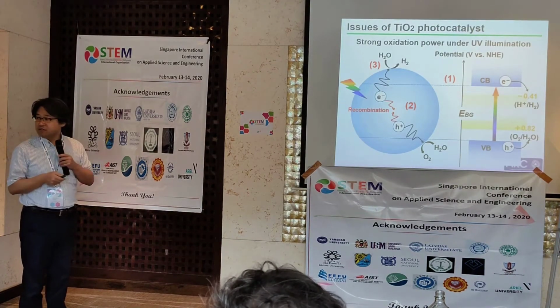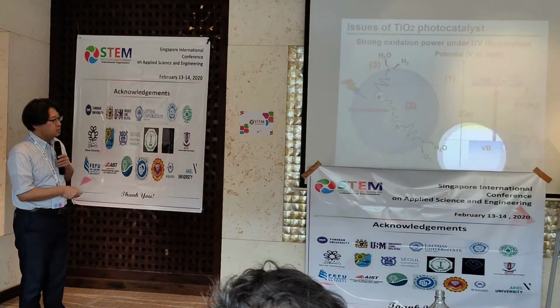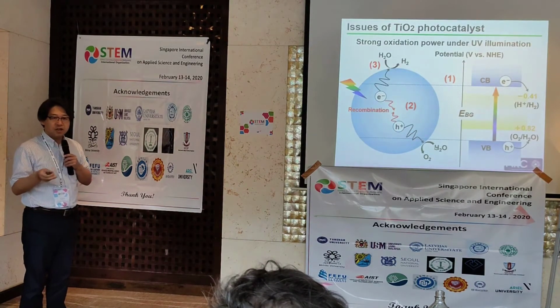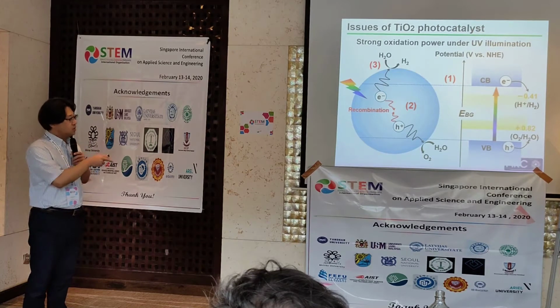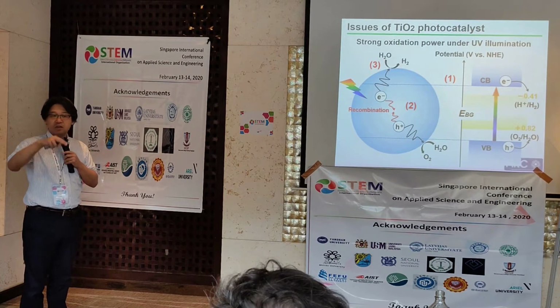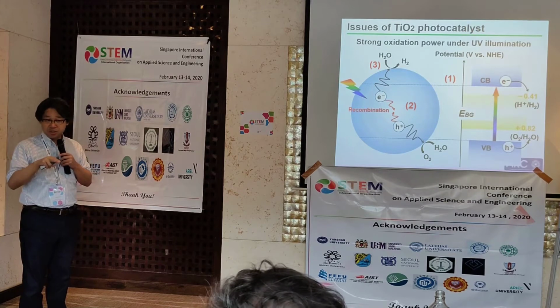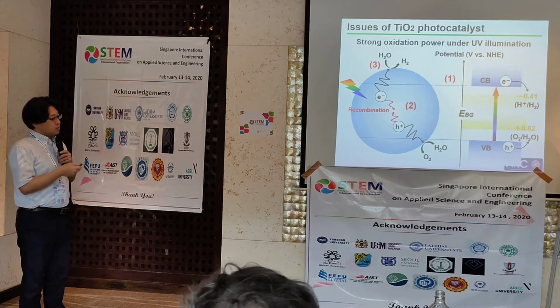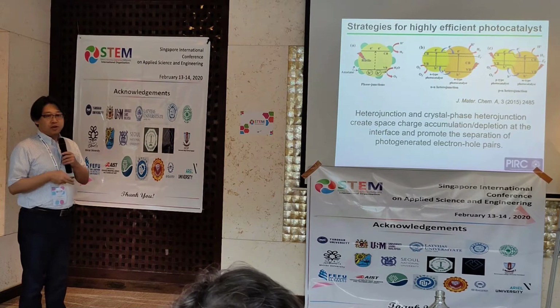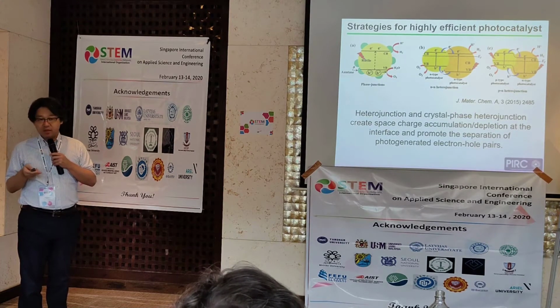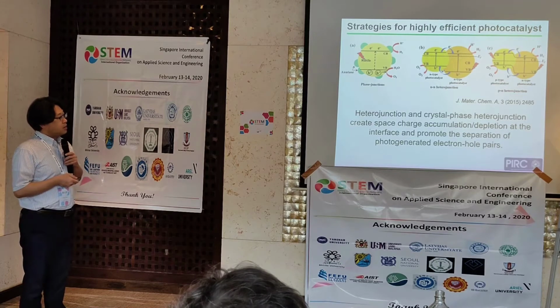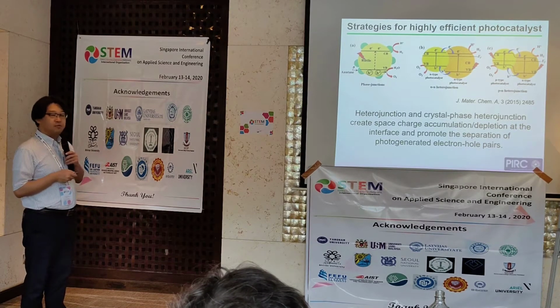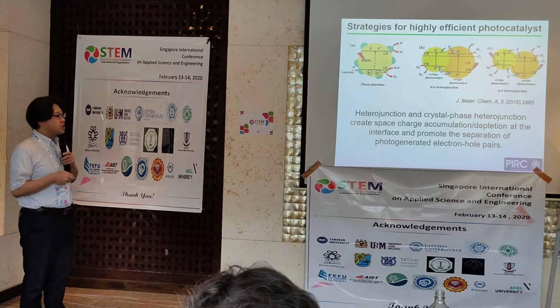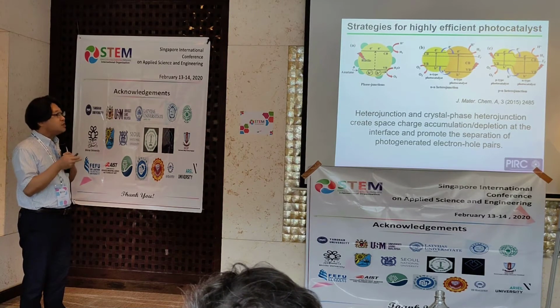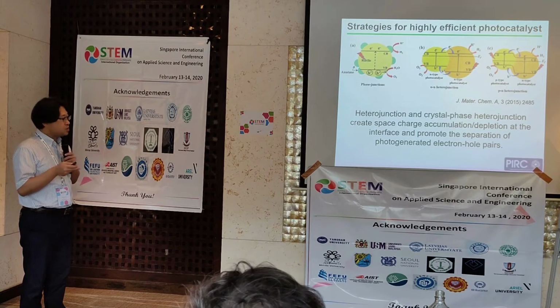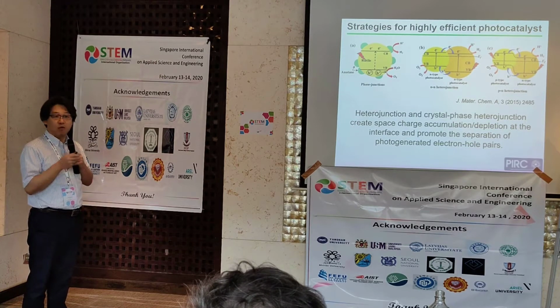So the important thing is to keep this valence band position. This is the originality of titanium dioxide because this valence band position has a very strong oxidation power. So to enhance this photocatalytic activity, in this paper they announced heterojunction and crystal phase heterojunction, which created space charge accumulation and depletion at the interface and promoted the separation of photo-generated electron-hole pairs.